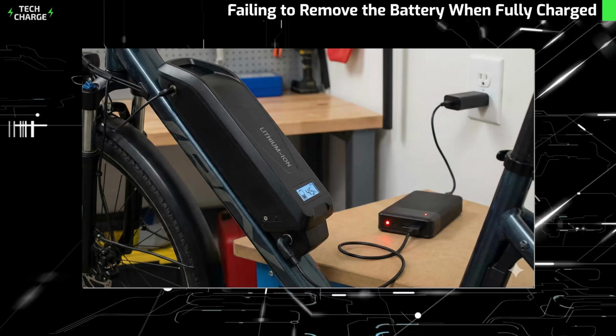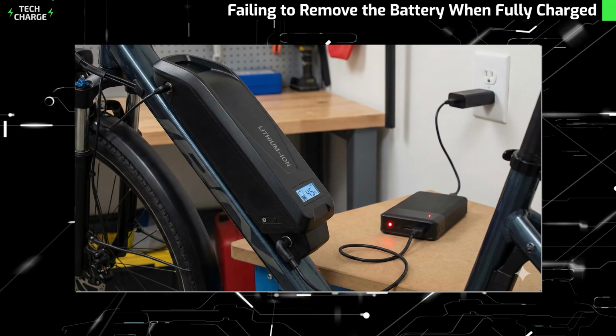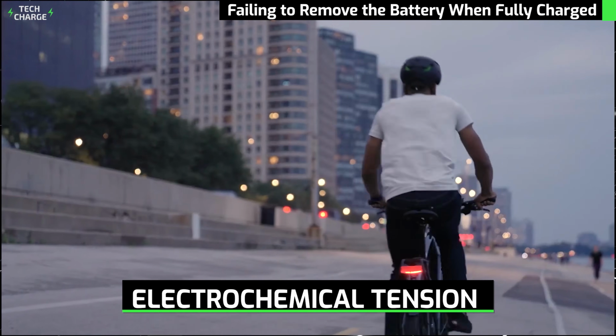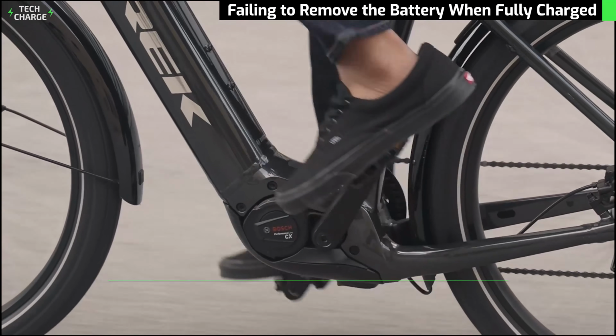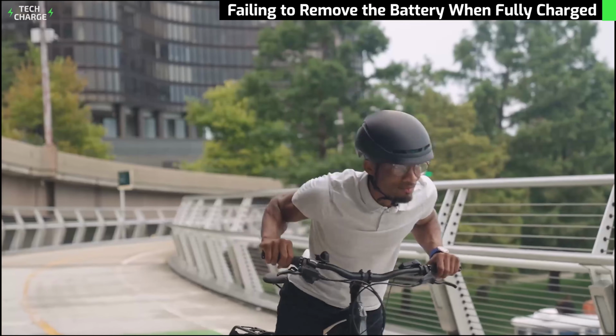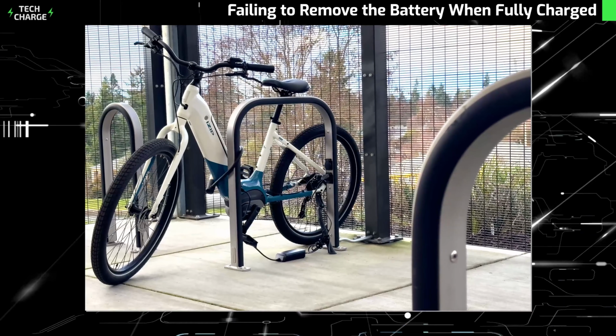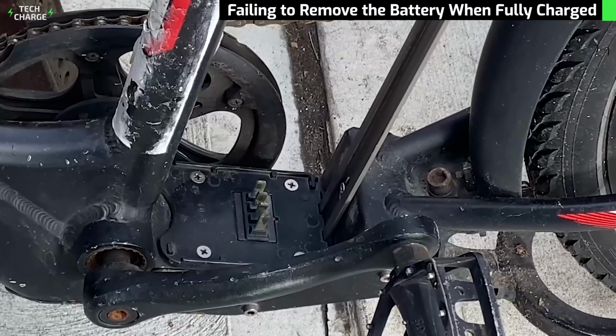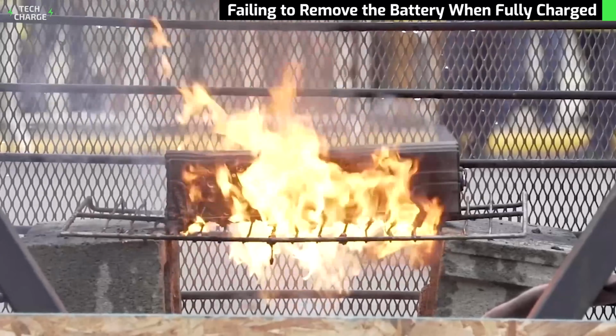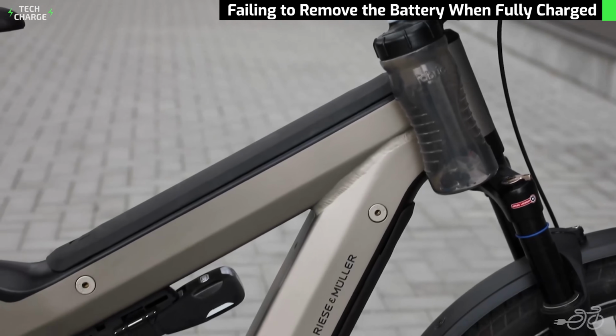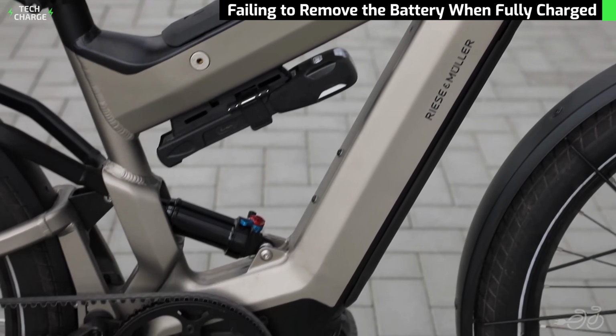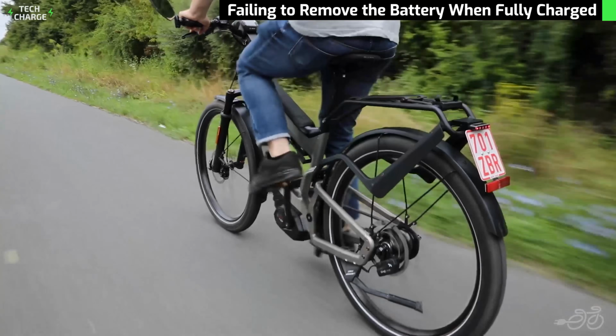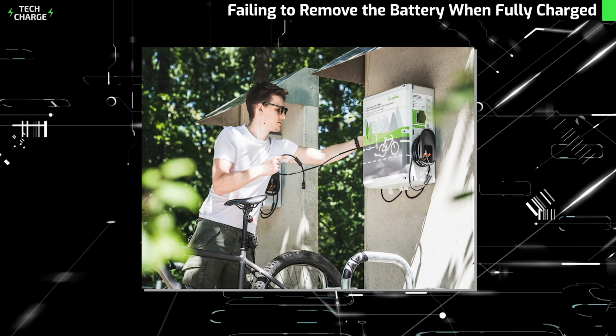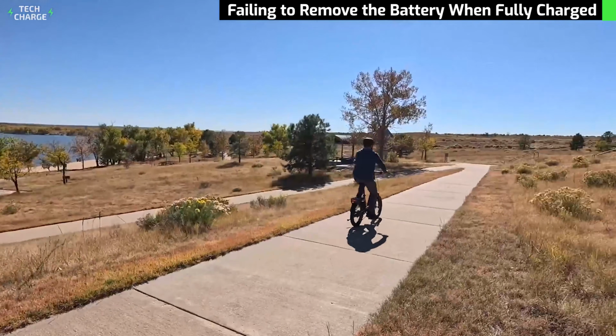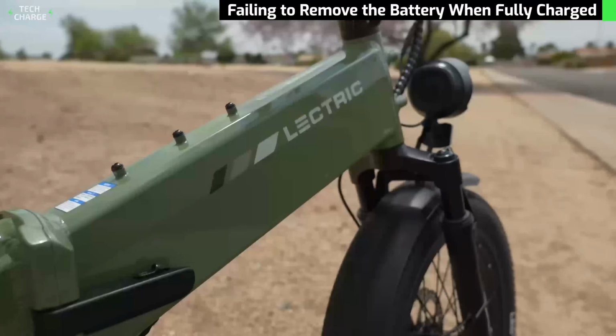Lithium-ion batteries don't like sitting at 100% state of charge for extended periods. The electrochemical tension at maximum voltage accelerates the rate of internal cell degradation compared to storage at mid-range charge levels. This prolonged stress compromises the structural integrity of the cells over time. While the immediate fire risk is lower than other mistakes on this list, the cumulative damage increases the probability of future failures. Battery researchers have established that the optimal charge level for lithium-ion longevity falls between 20 and 80%. Constantly pushing to 100% and leaving it there creates unnecessary wear. The cells are essentially under maximum tension, and that takes a toll on the internal components cycle after cycle.